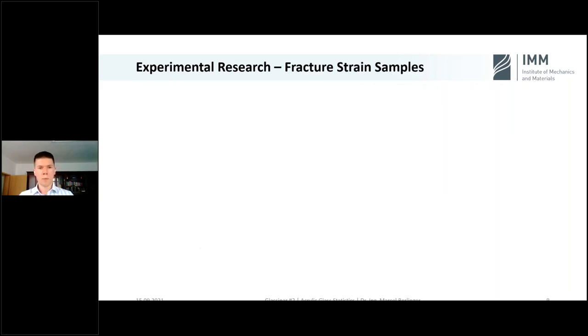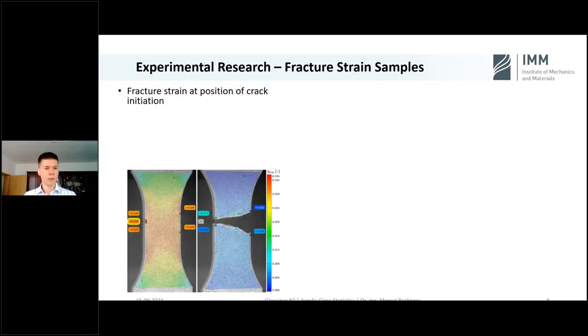Okay, but the important thing is the fracture strain samples I was getting together. Here, a picture of the analysis of the specimen. The colored surface indicates the strain, the true strain in the specimen, one picture before failure and one after. And the strain we took from the specimen as the fracture strain is the one right at the point where the crack developed.